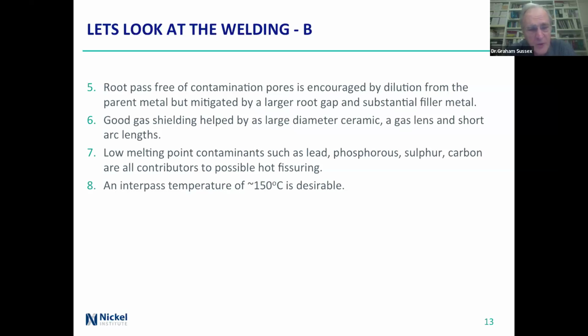And really, you want to look at an interpass temperature of no more than 150 or so, because you don't want the thing to stay hot for too long.